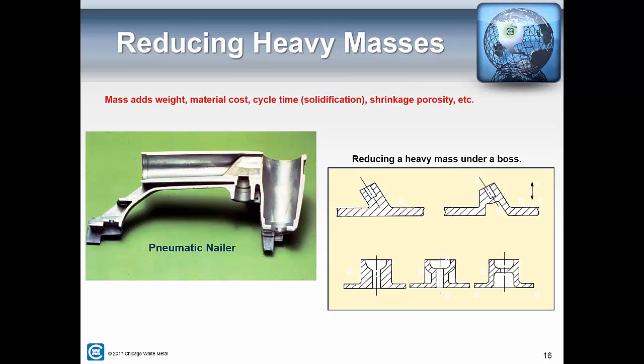The wall thickness topic from the previous slide, this just shows some techniques you can think about when doing a conversion or a completely new design. In the die casting world, a thicker wall section does not necessarily mean you're going to get a higher strength value out of it. What you'll see in the next slide as well is that the use of ribs and well thought out metal savers can actually increase the strength of your part without adding mass to it. The strongest section of a die casting is within the first 20 thou or so of the outer wall. It's what we call the skin of the die casting. As you go inwards, the material properties tend to be weaker. So if we can get a good consistent wall thickness for the given material and do some smart coring out of the thicker sections, you usually end up with a pretty strong part.